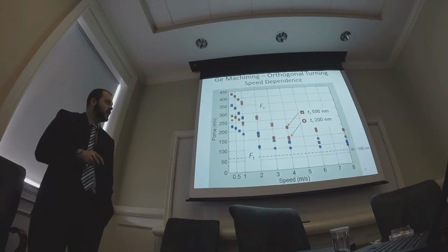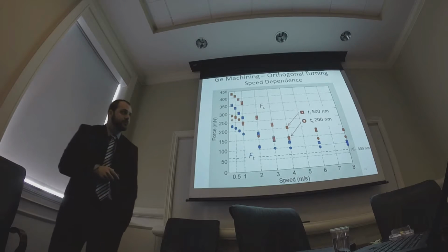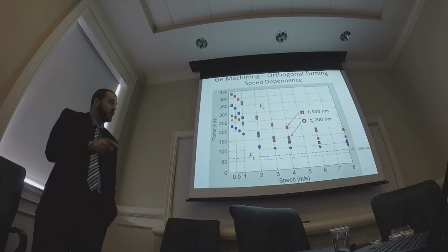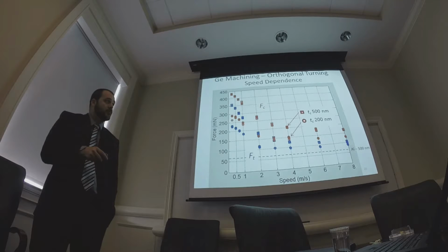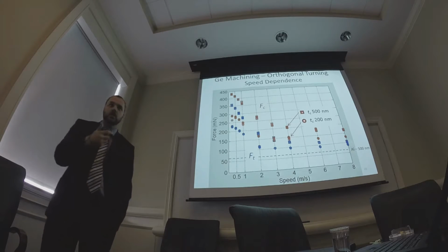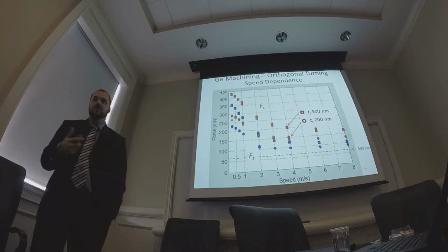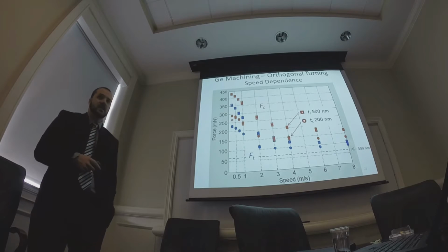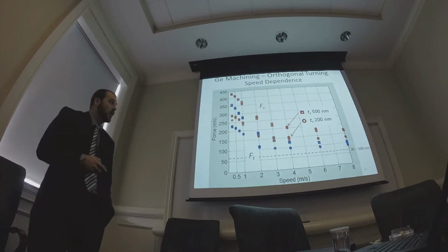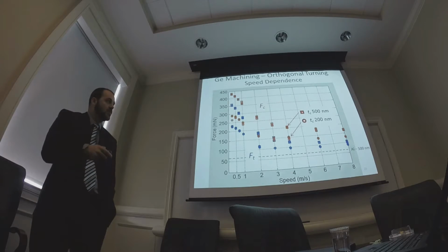Here we've got them combined together. For example, here's the cutting force of aluminum with a 500 nanometer chip. We're a good bit above that, but still surprising that we ended up down near aluminum, whereas germanium with round nose tooling was showing numbers more like hardened steel. So it's interesting, we go a good bit faster and our forces drop quite a bit.